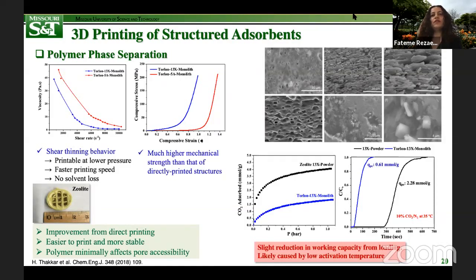So you can vary the viscosity by manipulating the amount of solvent that you add to your paste, and also the way that you add it. Sometimes you're required to add solvents dropwise. Sometimes you need to add solvent in larger quantity. So this is how you can vary the viscosity of your paste. Sometimes it's required to have a combination of different solvents in order to achieve the rheology or viscoelastic properties that you need to have a printable paste. So the answer is changing the way that you add the solvent, the type of the solvent, and the amount of the solvent that you need to prepare these pastes.